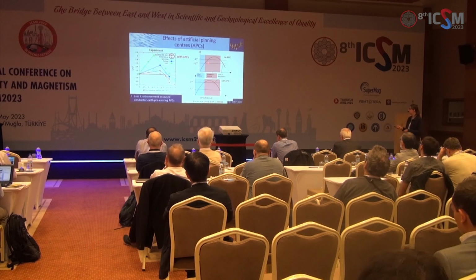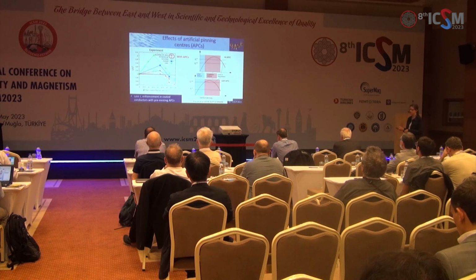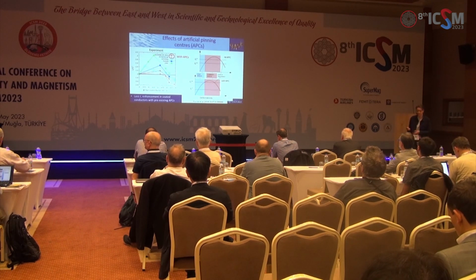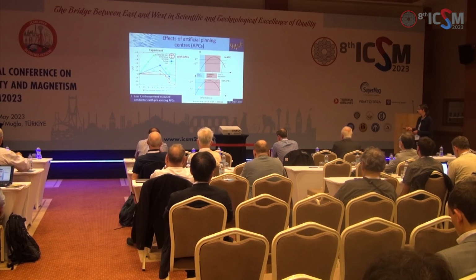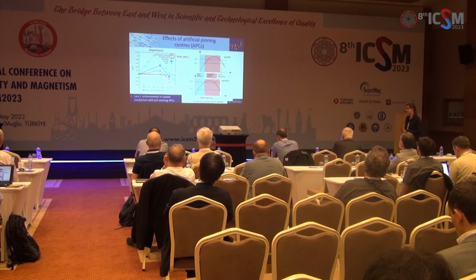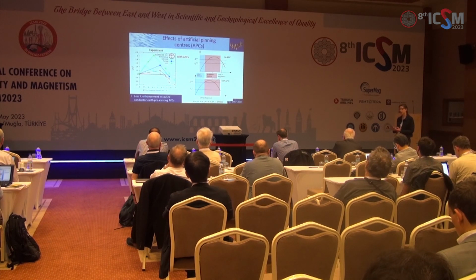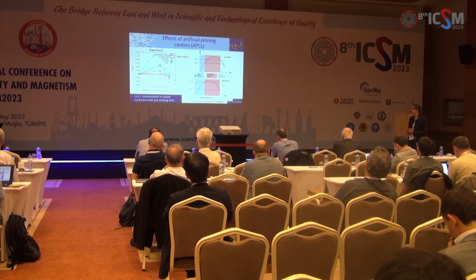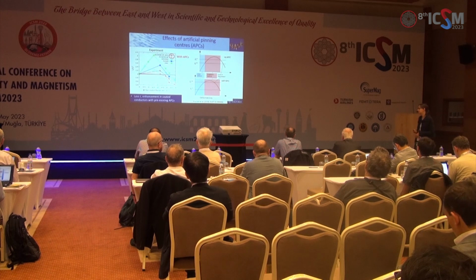The Vienna group have explained this by looking at the amount of damage you've got on this axis compared to JC. When you start, the material has some sort of defects already in there, and so JC is somewhere here on the curve, and when we irradiate, we push it up a little bit further before it gets worse again by adding these extra defects. However, if we were starting with an artificially pinned superconductor, we're already further up this curve when we start. We put extra pinning centres in to start with, so we can't get much more enhancement when we do the irradiation. That's the explanation of why you don't seem to get so much JC enhancement with artificial pinning centres.